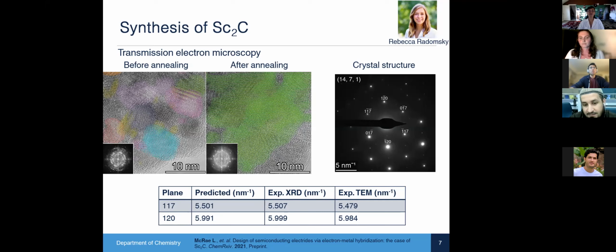Okay, no, my question is, you know the picture, the photo with the green bars? The green lines are different d-spacings, which means I believe there is another metal. I don't know if I'm understanding. After annealing, there are plenty of different d-spacings in the TEM image, which are not the same. Oh, I see what you're saying, that there are different crystal domains that are all in green. They're actually the same lattice spacings, they're just oriented differently. So we have slightly different orientations, but they're all part of the same crystal. I think they're overlapping, but they're 60 degrees from one another, which means that they all have the same spacing. Okay, thank you. Yeah.